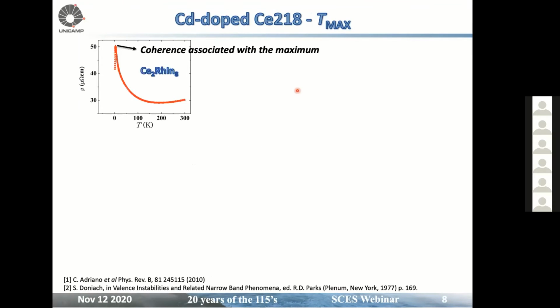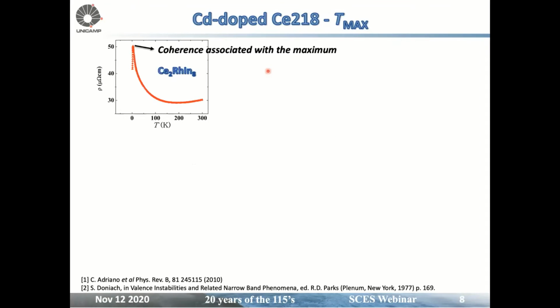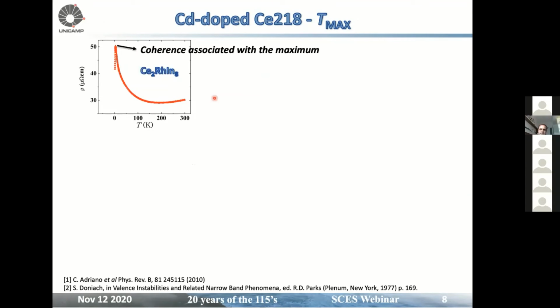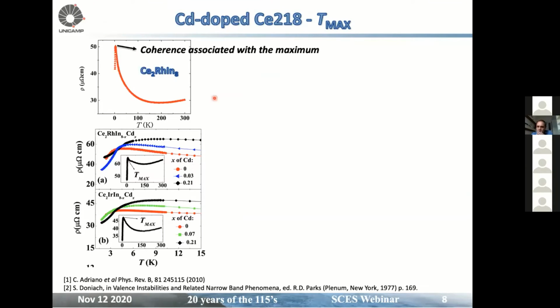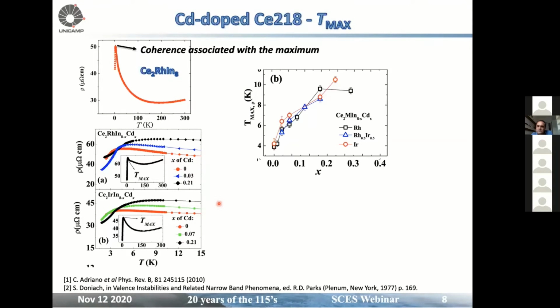And then we see what happened when we dope on the behavior of Tmax. This is the resistivity as a function of temperature for Ce2RhIn8, and that's the coherence associated with the maximum. So that's what I'm calling Tmax. Those are resistivity curves for both rhodium and iridium as a function of temperature for the dopings. And then if we plot Tmax as a function